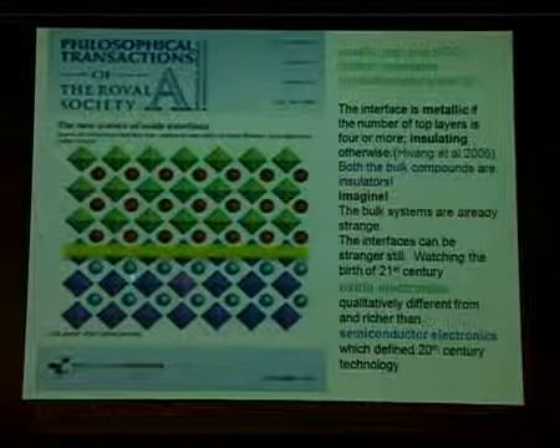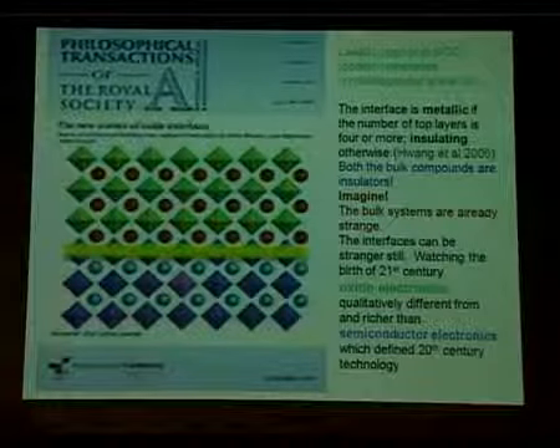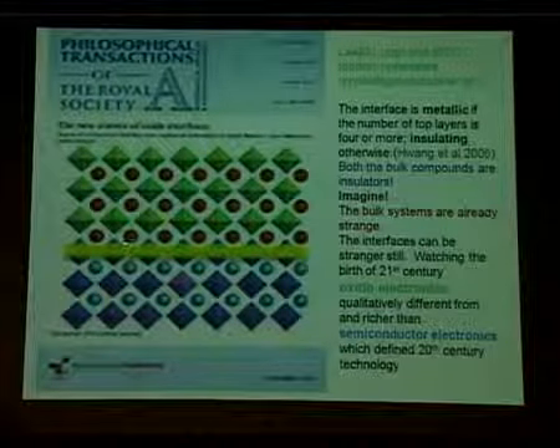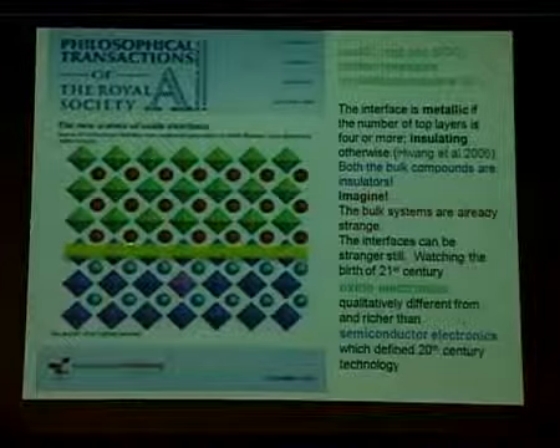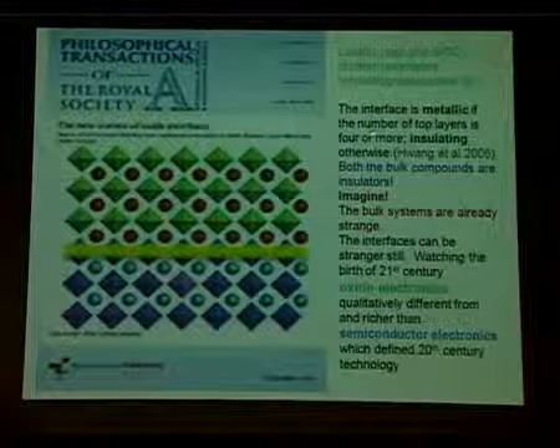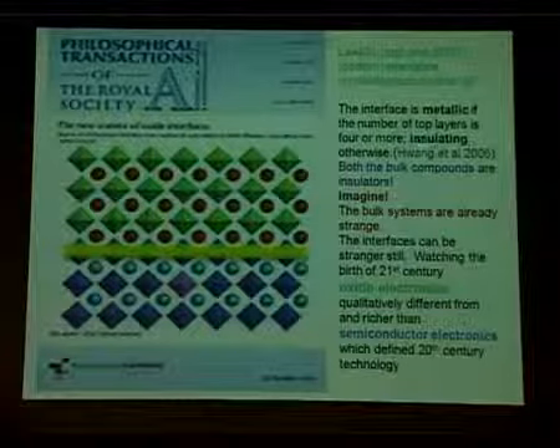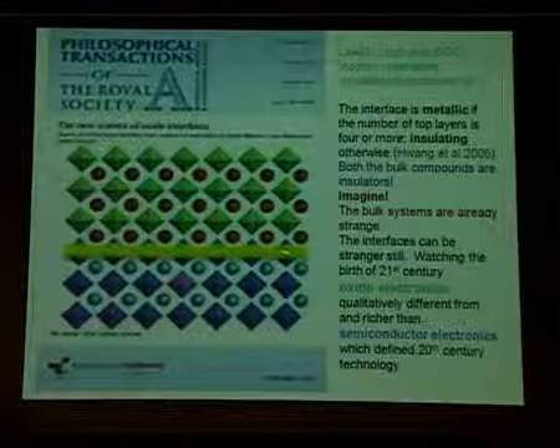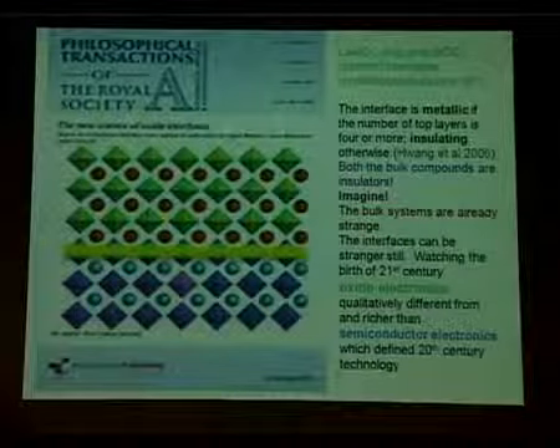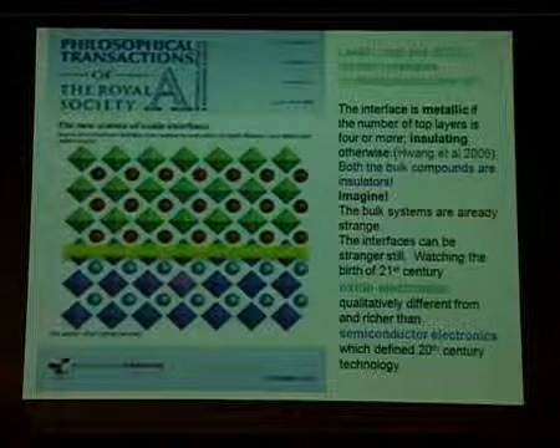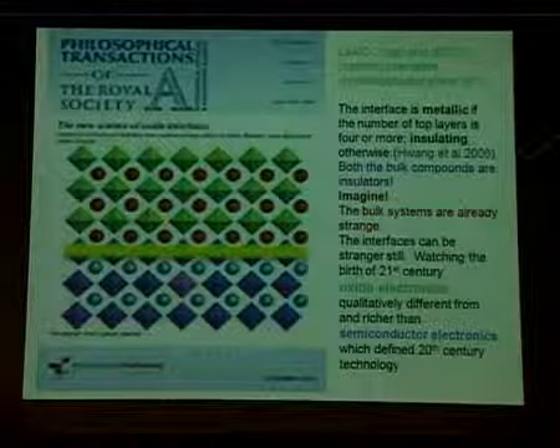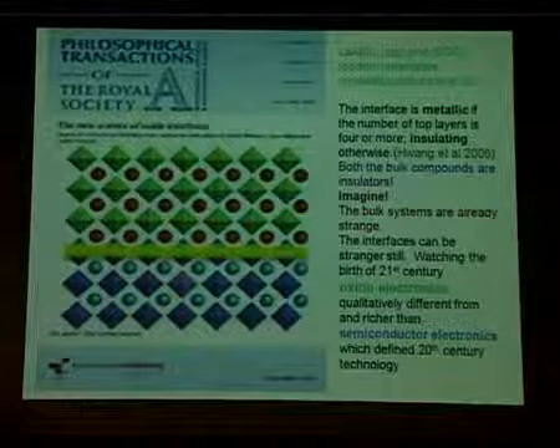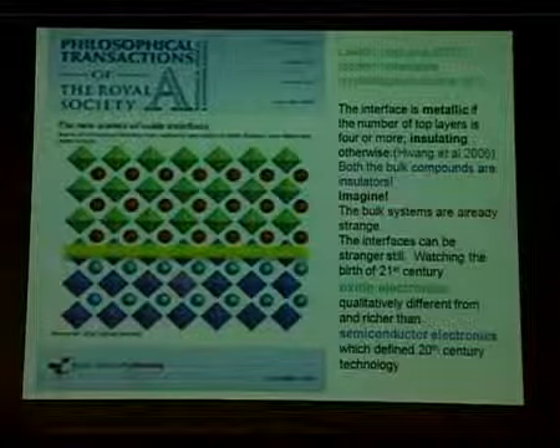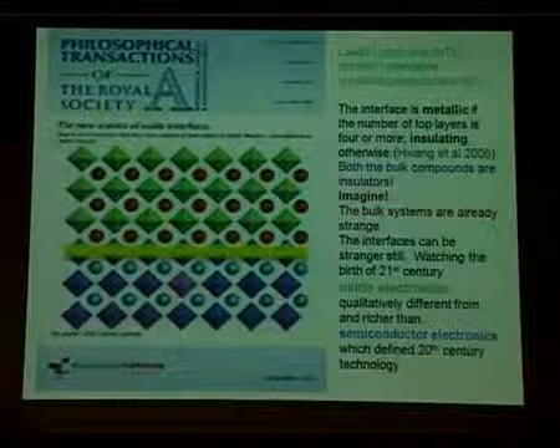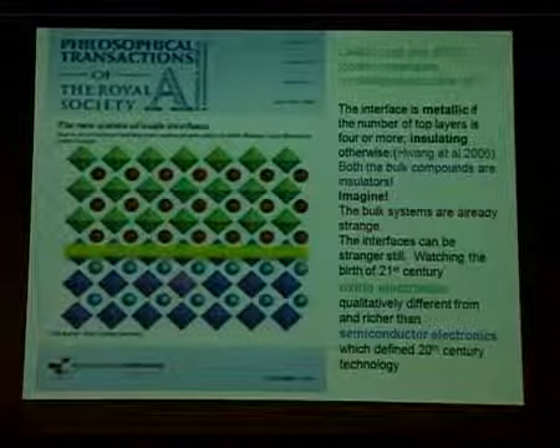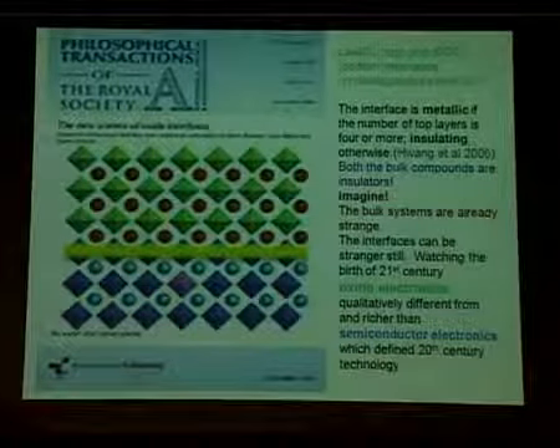So they did that, and they found something very bizarre. What they found was that if the number of lanthanum aluminate layers at the top is 4 or more, the interface is metallic. If it is less than 4, the interface is insulating. Now this is interesting because the parent compounds in the bulk, both of them, are insulators. So it is funny that you take two insulators, put them together, and the interface becomes metallic.